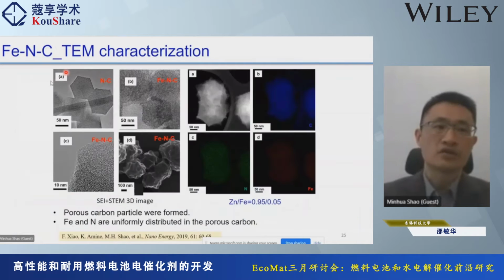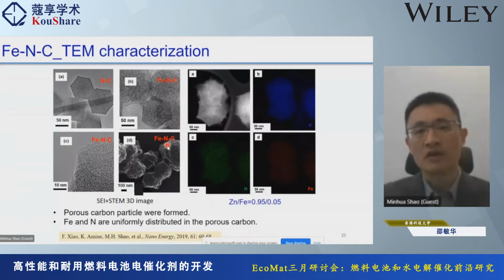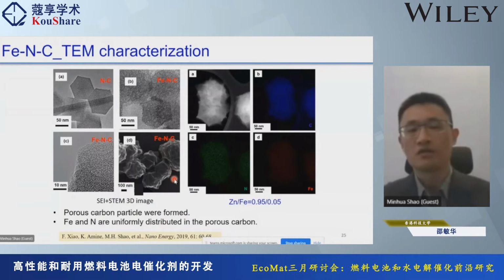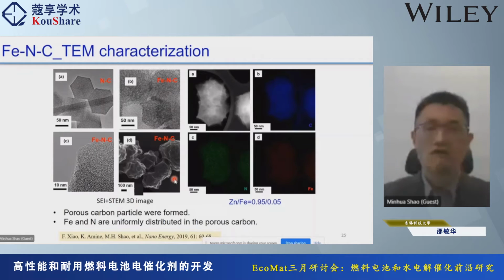Okay, so this is the characterization of the iron nitrogen carbon. So basically, with an iron doping, okay, you can see that even though the morphology changes significantly, more or less the ZIF structure is still there. If you do this STEM, you find that this is not a very smooth surface. Okay, so this is a rough surface. So this is basically the carbon, and you dope some iron nitrogen into it. Okay, so this is good because it can create a larger surface area for further platinum supporting.